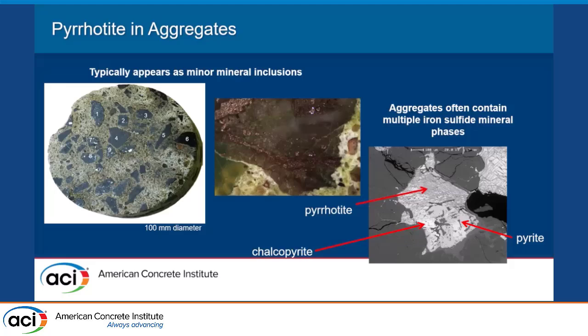If you go to this grain in particular, you're looking at this little guy here, and you bring it over, and this is less than 1/2 millimeter in size. Now, if you notice, this is inside of the particle, not the outside. So if we're doing our standard C295 and we're just looking at the grains, if it's not rust colored, rust stained, if you don't have that mineral on the outside, it's going to be really hard to know if there's actually an iron sulfide in there. So that's the first complication.